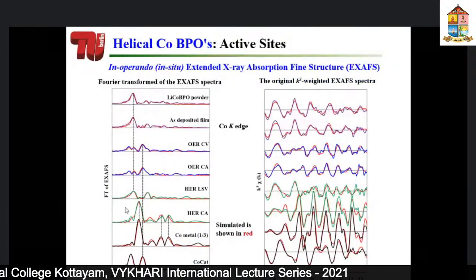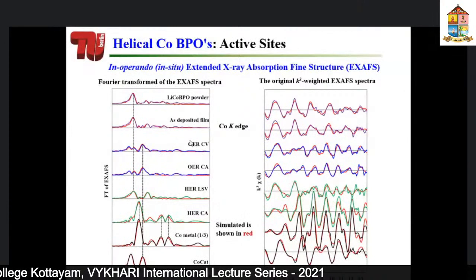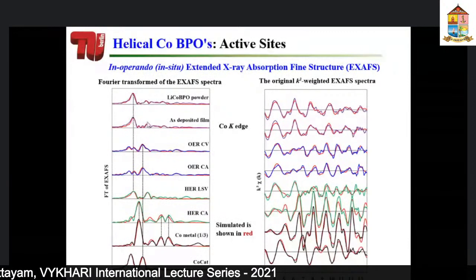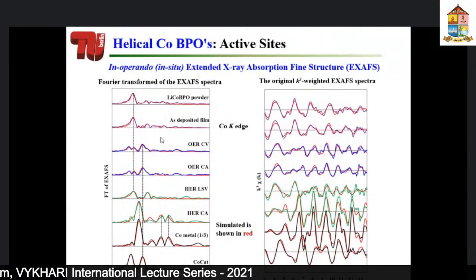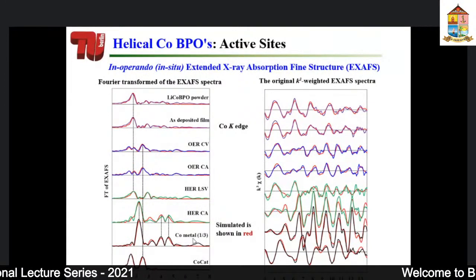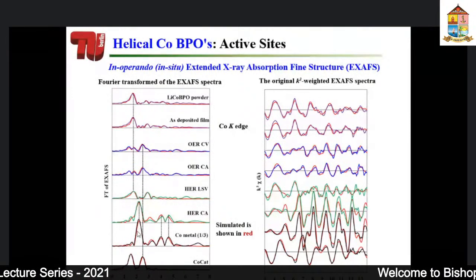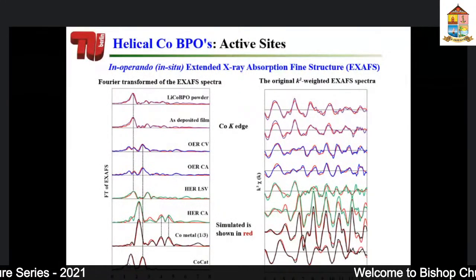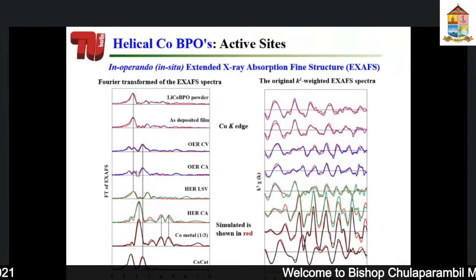Okay, this again looks complicated, but you don't have to worry about it. What exactly it says is that we had a structure with a particular composition, and after the oxygen evolution reaction, the structure changed to a different structure. Similarly, in the case of hydrogen evolution, it also changed to a different structure. So we also compared with cobalt metal, which exactly matches after hydrogen evolution, and also we used cobalt oxyhydroxide, which also somehow matches the structure after the oxygen evolution reaction.